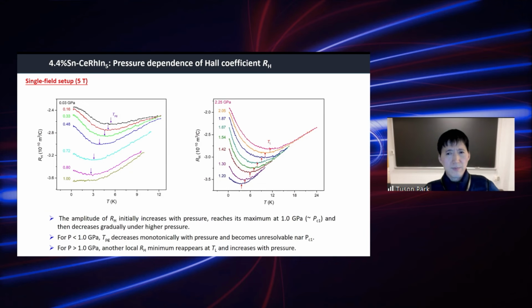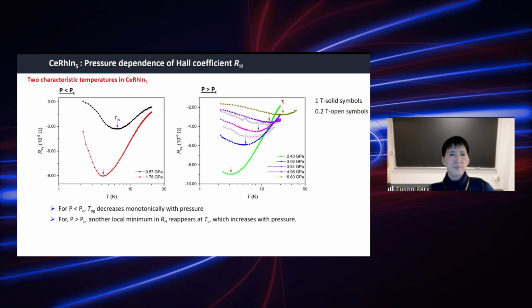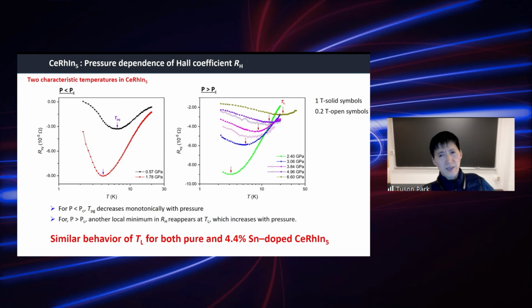is going on. And this is the Hall coefficient for the pure compound, and at temperatures below the AFM QCP point, you can see that the pseudogap temperature decreases with increasing pressure. And when the pressure is higher than the critical point, then you can see an additional point, a new type of minimum occurs in the high pressure region, which is similar to the 4.4% compound.